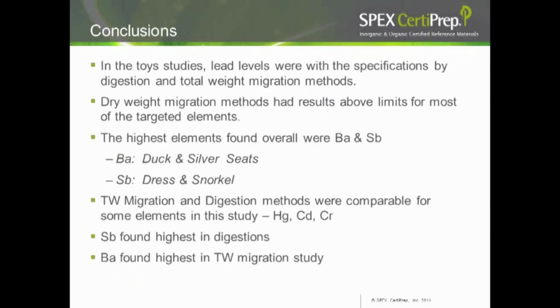Our dry weight migration methods had results far above all the limits for almost all the targeted elements, and I have some suspicion that this is probably not the best way of trying to calculate this type of information. The highest elements we did find overall were barium and antimony, with barium being in our friend the rubber duck and in the silver seats of the car. Antimony being in the dress, and a little bit concerning was also in the snorkel. The total weight and the digestion methods were comparable for several elements, including the cadmium, the chromium, and the mercury. But what we did find was the antimony levels were often highest in the digestions, while barium seemed to really migrate quite well into the extracts. So for the migration studies, barium was the highest.